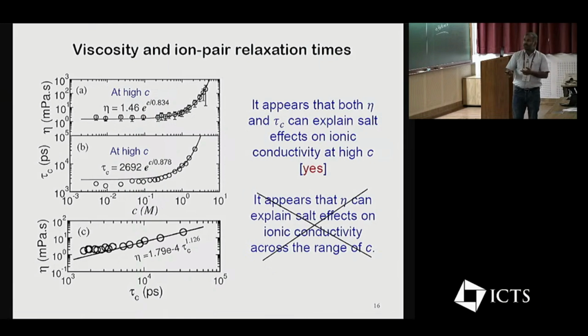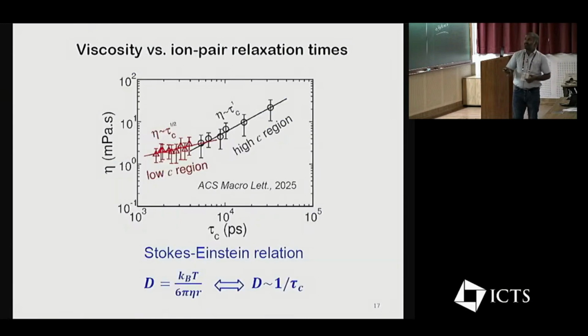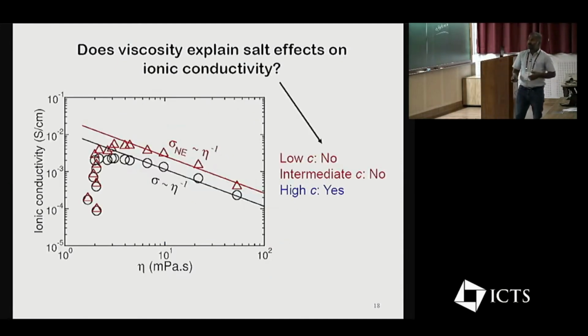In fact, if you dig in a little bit deeper, we notice that only at high concentrations is there a one-to-one correspondence between viscosity and tau c, but at low concentration, we have this particular relationship. So we can think of what the implication could be for ionic conductivity. When I calculated ionic conductivity and plotted it against eta, we see that at high concentration, yes, this can be explained within the framework of a Stokes-Einstein-like power law, but at low concentration, no.